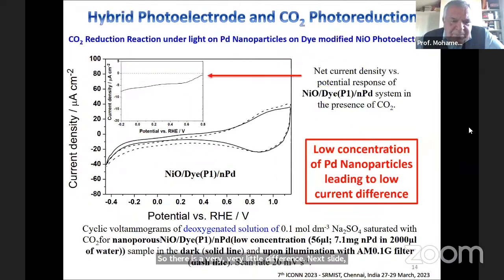Next slide, please. Finally, we take the hybrid photoelectrode where we absorb the palladium nanoparticles on the dye-modified nickel oxide electrode, and we check if there is CO2 photoreduction. And then we can see a little effect which started earlier, where the black solid line is under dark, and the dash line is under light. As you can see, there is a little difference, but we check it.